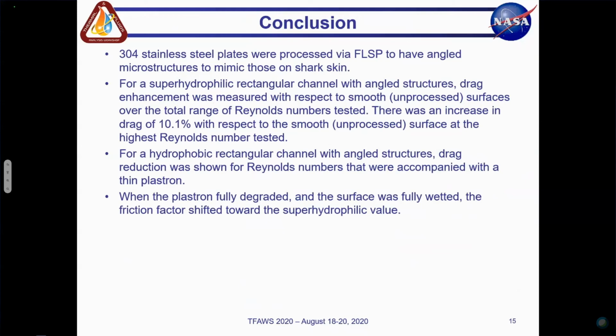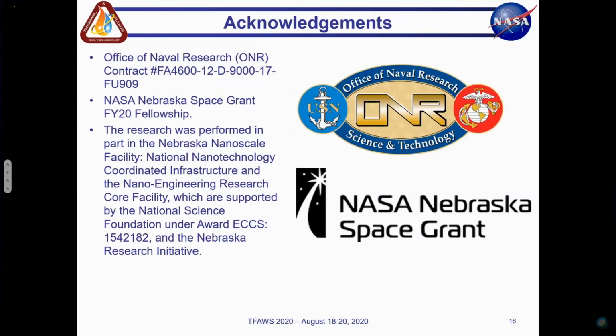And then as the plastron starts to degrade and fully wets, you see the friction factor shift to the super hydrophilic. Though it is important to note that the friction factor does not cross or come in contact with the super hydrophilic value. You still have this slight change in wettability that accounts for the small decrease in friction factor.